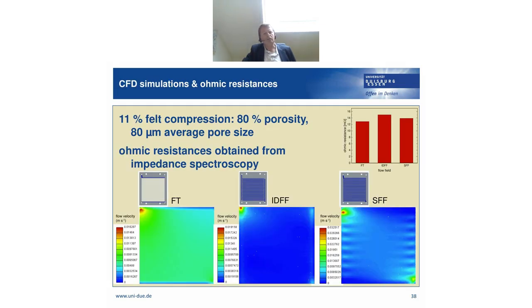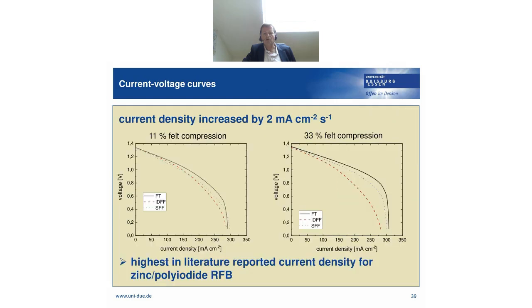We did some simulations on the flow velocity distribution for the 3 flow field designs. We did measurements of the ohmic resistance with the help of impedance spectroscopy. And you can see here qualitatively in the 3 simulation diagrams the flow velocity distribution.